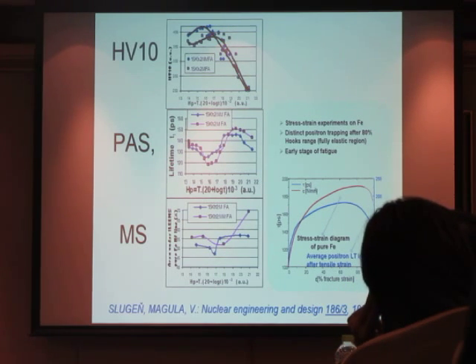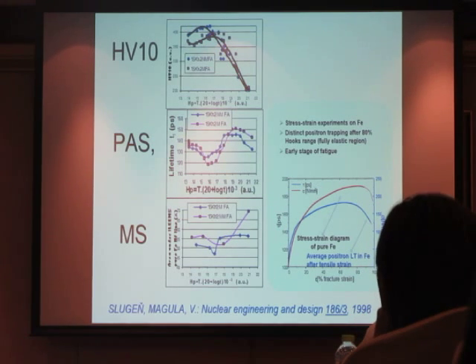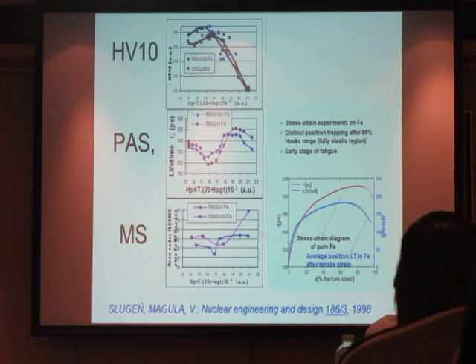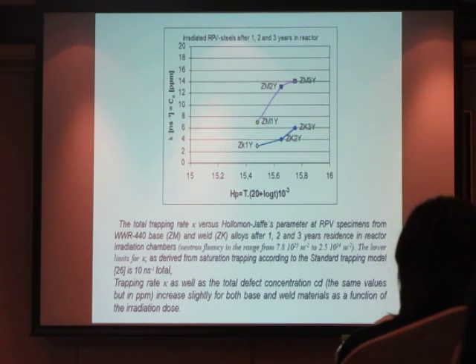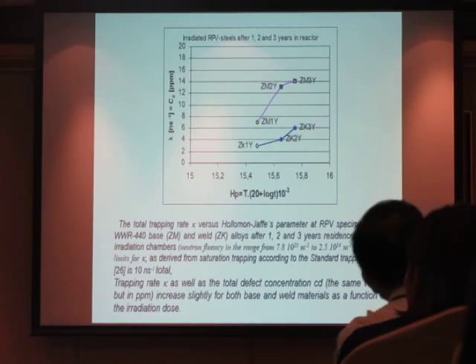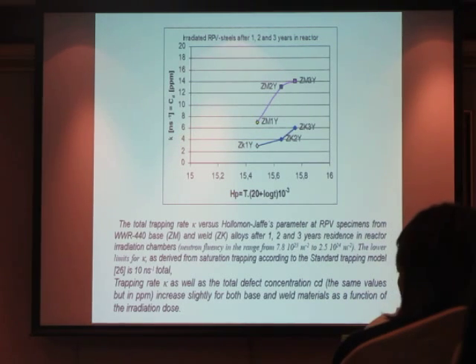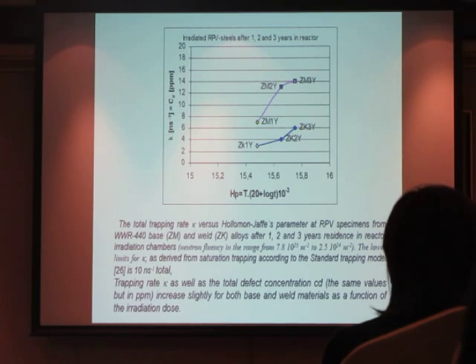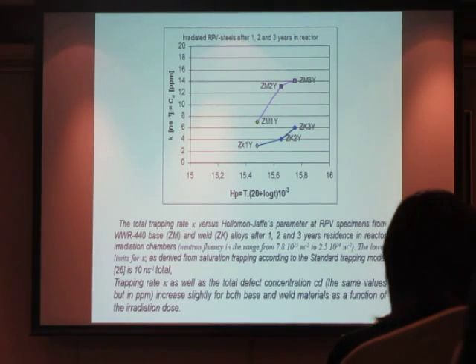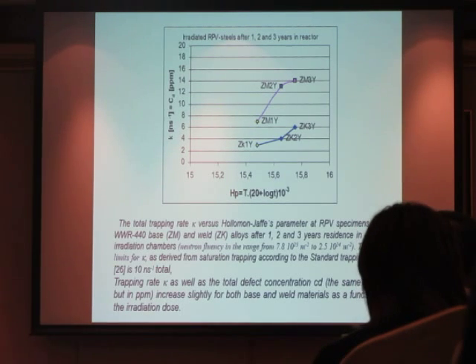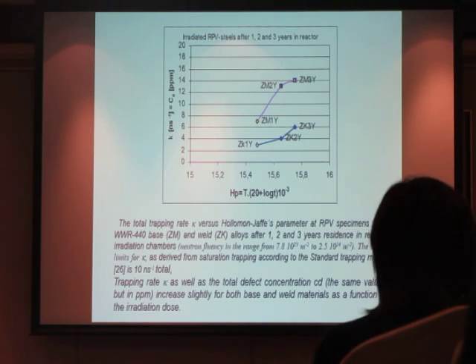Because we are thinking about treatment during, let's say, 30 or 40 years at a different temperature, this Hollomon-Jaffe parameter enables this calculation. Also, we can calculate the level of destroyed material, and the concentration of defects. In the case of the presentation of Mr. Naga yesterday, the concentration in the Japanese steel was on the level of 1 to 2 defects per 1 million. In the case of irradiated Russian steels, we go up to 15. We have a little bit higher neutron flux and also fluence.